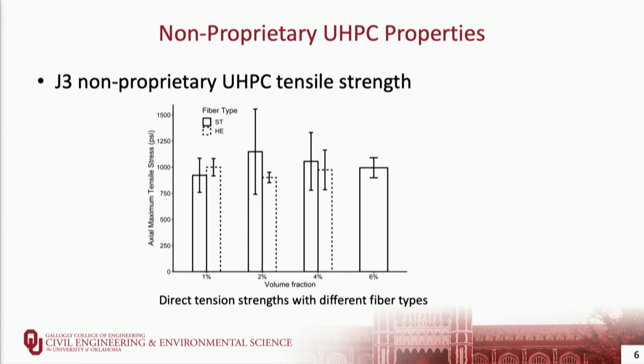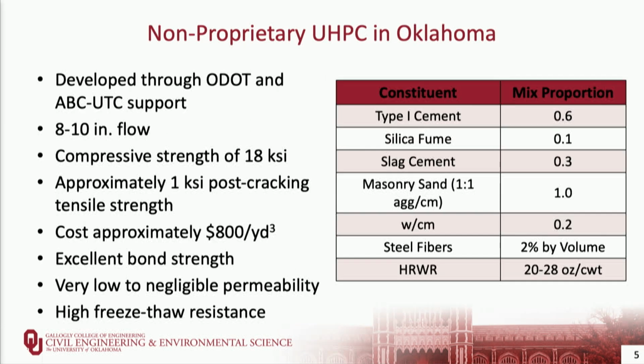So we looked at some different fibers as well. This is a plot giving you an example of direct tension strength. Instead of flexural strength, you often measure direct tension strength with UHPC. In this case, the black line bars use the typical straight fibers that are included in most UHPC, and the dashed line bars are hooked fibers. We can see that we typically get similar performance, but the tension strength is usually a little higher when we use the typical straight fibers for UHPC.